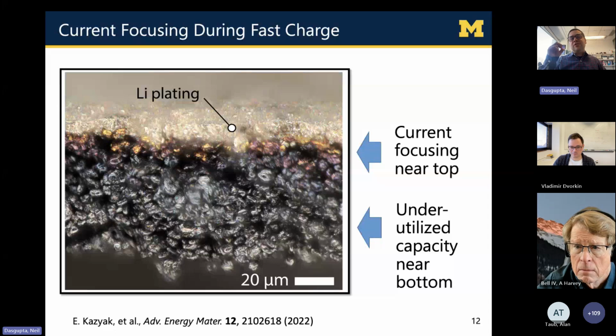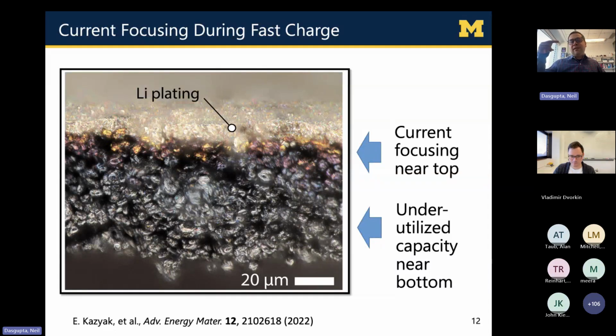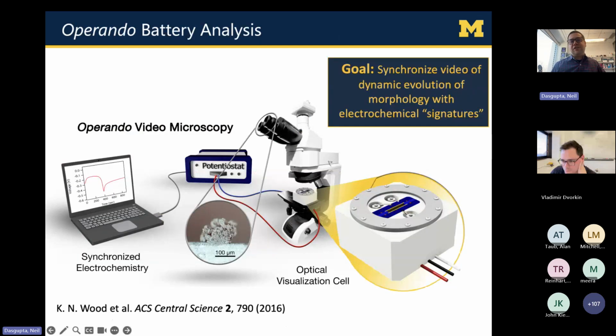The graphite starts out a grayish black color. As we add more and more lithium in as we charge it, it transitions from gray to blue to red to gold. Because we're looking at this cross section, we can see that not only do we have this lithium plating at the top surface, but the reason for that is I quickly charged the top surface of my graphite electrode, while those graphite particles in the subsurface region underneath are dramatically underutilized. I'm not able to put the lithium deeper into the electrode under these fast charging conditions.